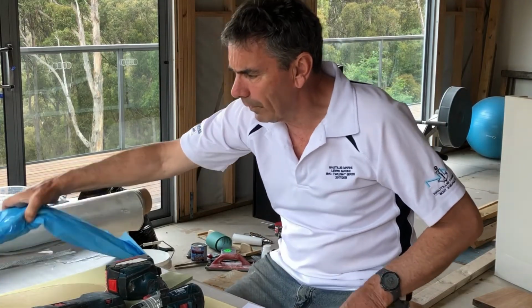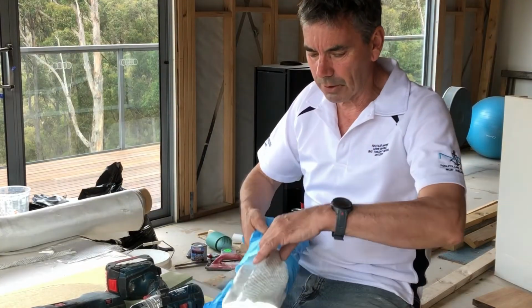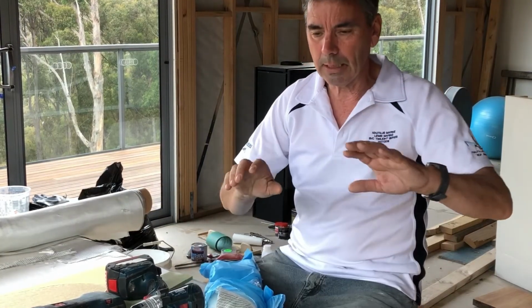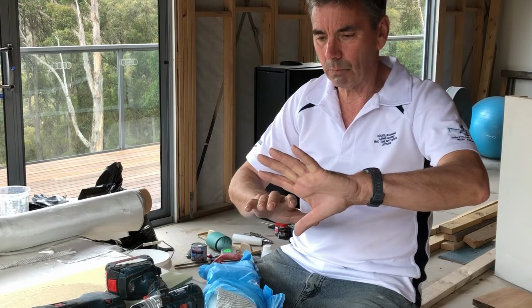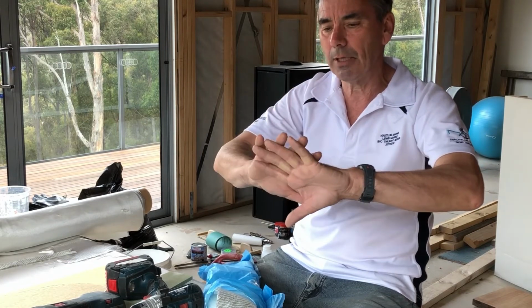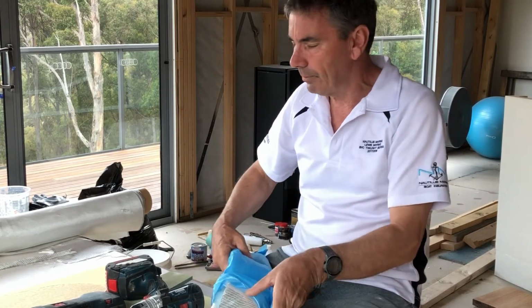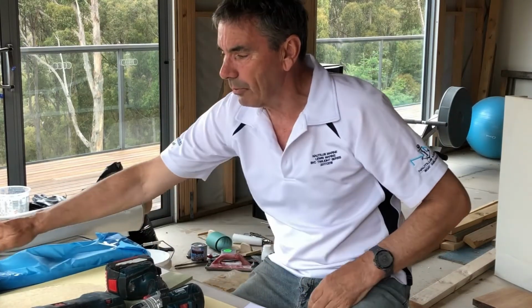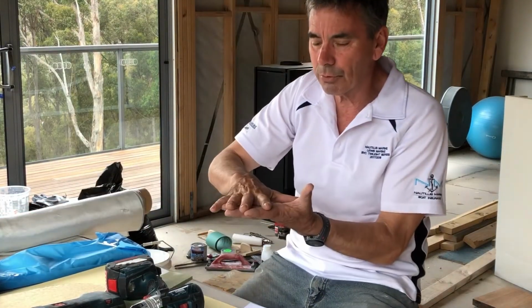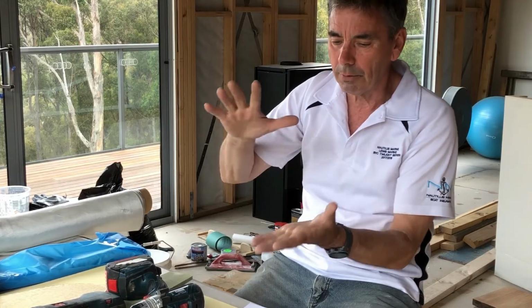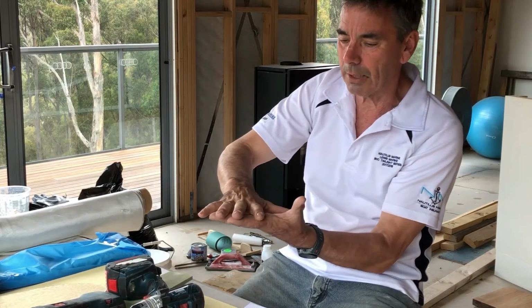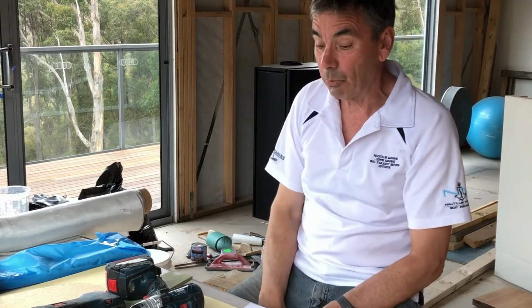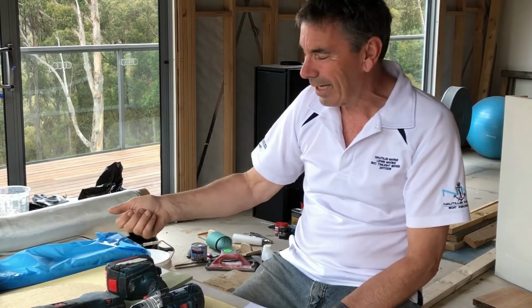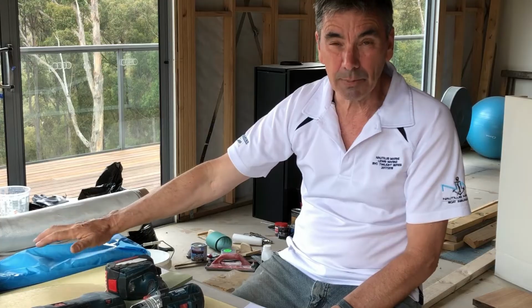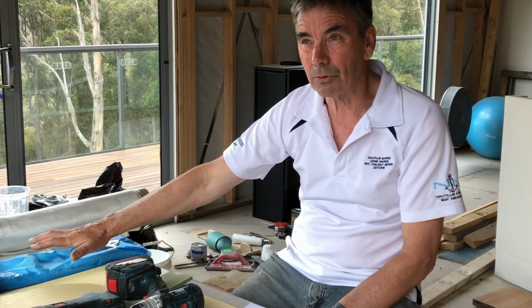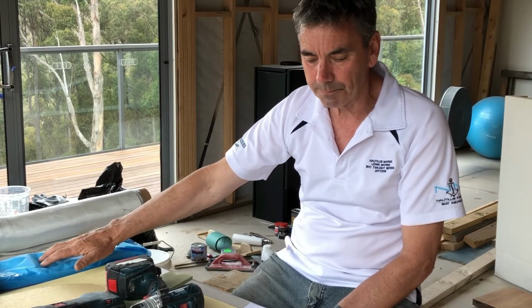Somebody used 450 double bias, which is a great material. So it's got the glass running 45 degrees that way and then 45 degrees the other way. You get a really good glass to resin ratio because they're flat bundles, just stitched together. They're not woven. They're just flat bundles that way, flat bundles that way. So that works really well. But we now think maybe that 450 it makes the boat a bit heavy. So you might have to be careful in not using too much of that.